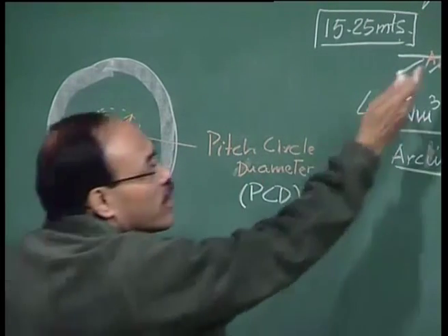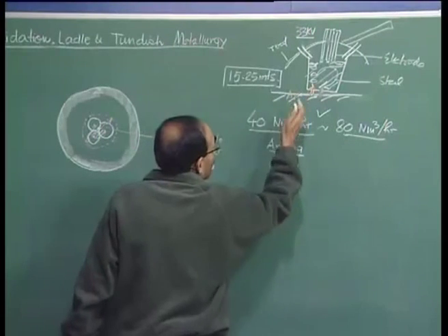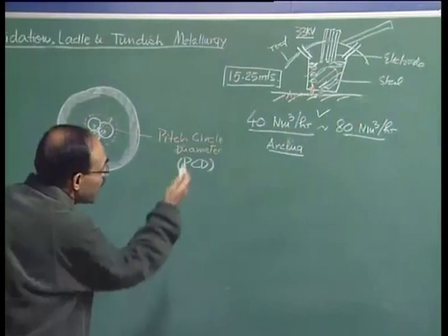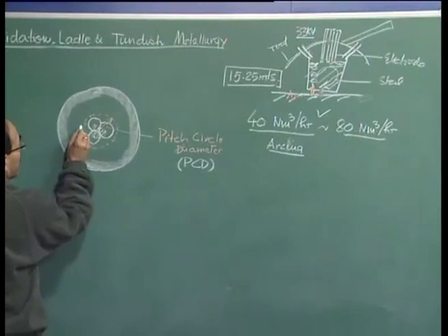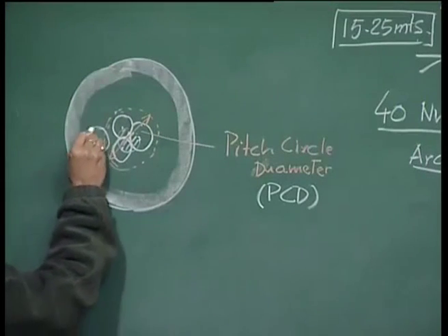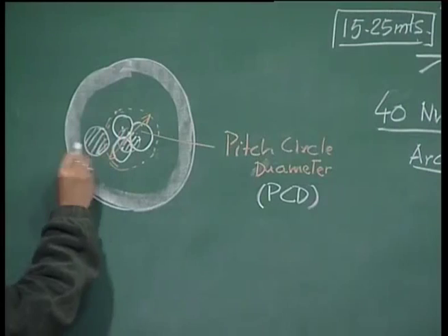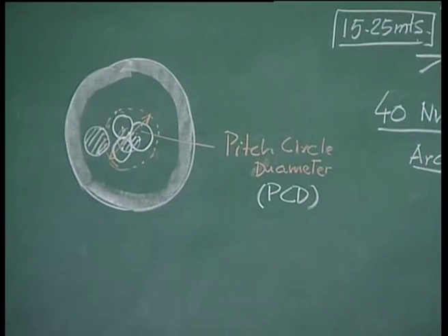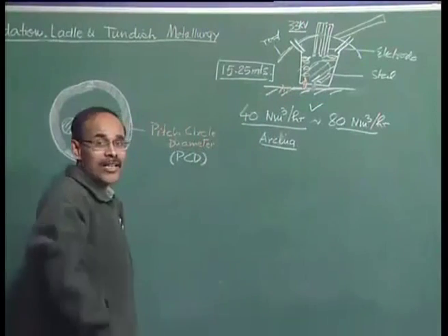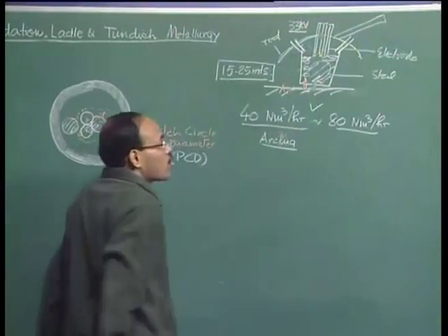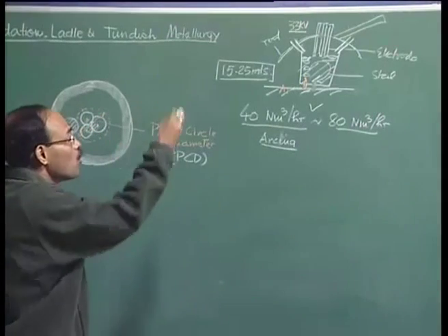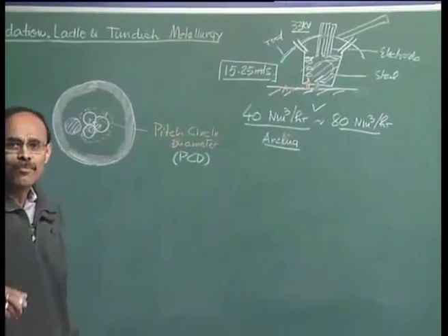On the other hand, if the porous plug is located a little bit away towards the wall itself, in that case I can see that the area in which the plume is going to be surfacing will be represented by this hashed area. So, by displacing the porous plug towards the wall, it is possible to prevent direct contact of the surfacing plume with the electrode.